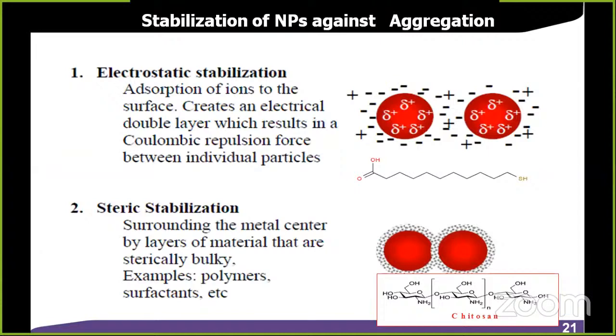If you see these values, the instrument is called a particle size analyzer. If you give your solution, you can measure the surface charge. The surface charge will come in millivolts: minus 20 millivolt, minus 30 millivolt, plus 30 millivolt. That is the surface charge. And there are some rules. If the surface charge is more than plus or minus 25 millivolt, the particles are highly stable. If nearly 50, more stable. It is very rare to go for more than 50.